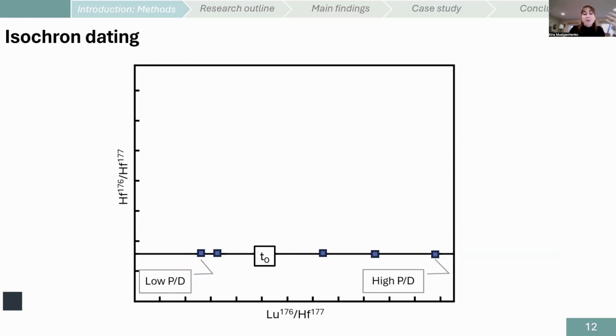When I'm talking about isotope composition of the system, I mostly refer to this particular ratio. So at the time of the forming of the assemblage, all of the different minerals that are part of this assemblage have the same ratio of hafnium-176 to hafnium-177. What is different is the parent-daughter ratio, so it's a ratio of lutetium to hafnium. It is different because those are different chemical elements and different minerals prefer one to another. Like garnet prefers lutetium to hafnium, so its ratio is going to be high. And clinopyroxene prefers hafnium to lutetium, so the ratio is going to be low. That spread is what is going to give us the good precision on the isochron later.